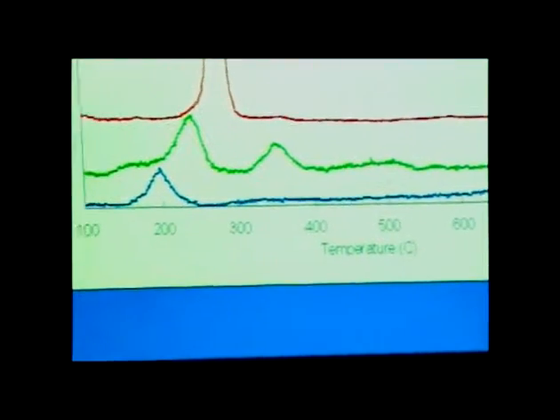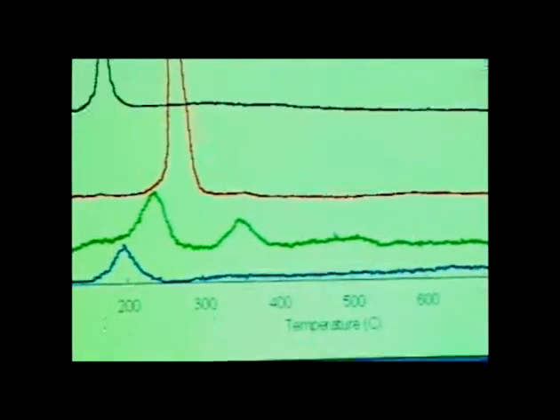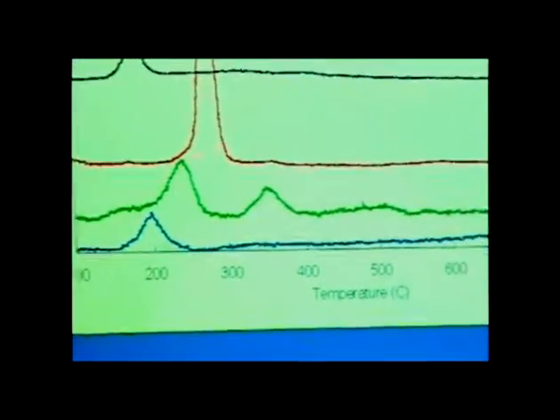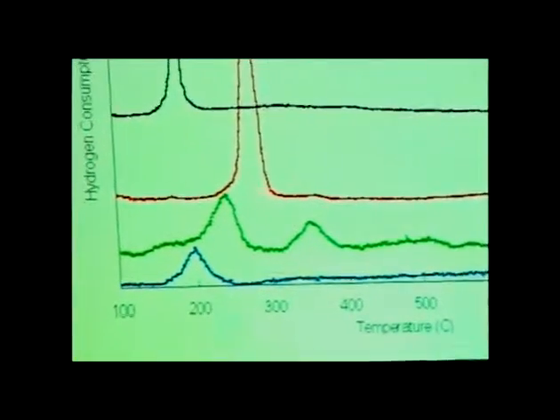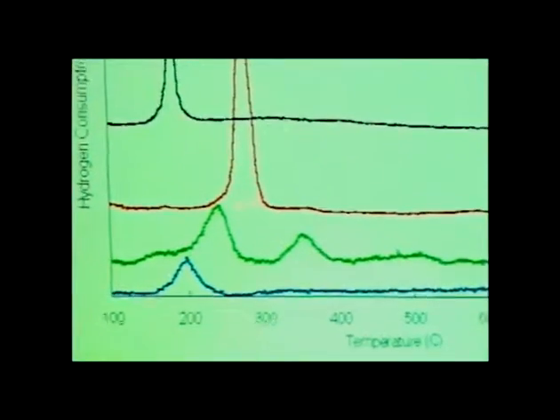And we also see the reduction of the formation of this peak here, which is most likely due to the reduction of the lanthana material. If you look at the lanthana ceria promoted catalyst here, we have now a very sharp peak, which is at higher temperatures, about 270 degrees, and the amount of hydrogen that's consumed here is approximately equal to the amount of hydrogen for this peak and the amount of hydrogen for that peak.